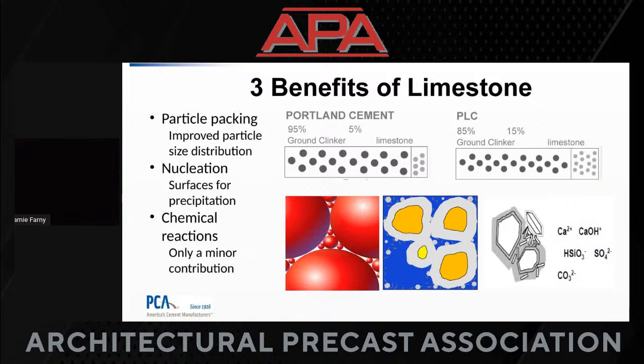So that's one aspect that really plays into strength gain because we have such a tight, dense matrix. We can get improved strengths because of that. The particles are actually in contact, particle to particle contact. That's one reason. We also have, as a result of that, lower permeability generally in Portland limestone mixes. So most durability issues are something trying to work its way into that concrete matrix. So it's water and aggressive ions that are carried in with the water. So if we've got a tighter matrix, we can often see improved durability. So that's the first thing that limestone is doing.